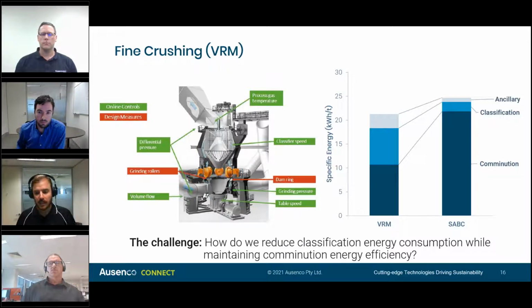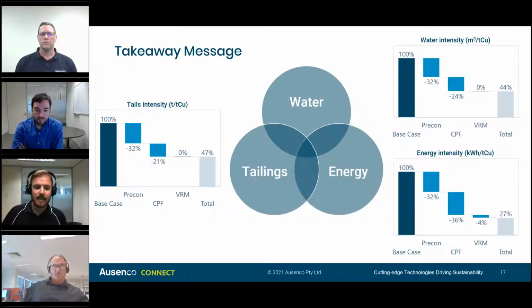perspective, the comminution energy, as you can see on the graph on the right-hand side, is almost half of what you would see in an SABC or a SAG milling circuit. However, when you take into account the fan and the heating requirements in the VRM, which is the classification and ancillary energy, the reduction actually becomes much less, only about 20%. So the challenge really is, how do we reduce classification energy consumption in these technologies while maintaining the comminution energy efficiency? So we want to reduce the lighter blue bars there without increasing the dark blue, which is a real challenge. So if we go to the final slide, there are some takeaway messages.